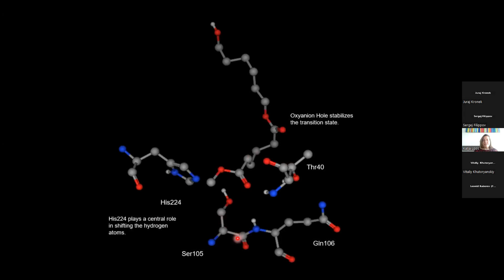And I want to show you shortly the mechanism of all these hydrolases, because we come back to that later also when we discuss results. So they are also called serine hydrolases because in the active site, the most important amino acid is a serine. In our case, this is the structure of CAL-B, the Candida antarctica lipase B. We know that the serine is amino acid 105 in the whole sequence. And this is, of course, not the whole enzyme. The enzyme is a big globular thing. This is an extreme zoom into the active site. You will see that this histidine is very important because it accepts hydrogen. And we also know that we have different groups which stabilize transition states.